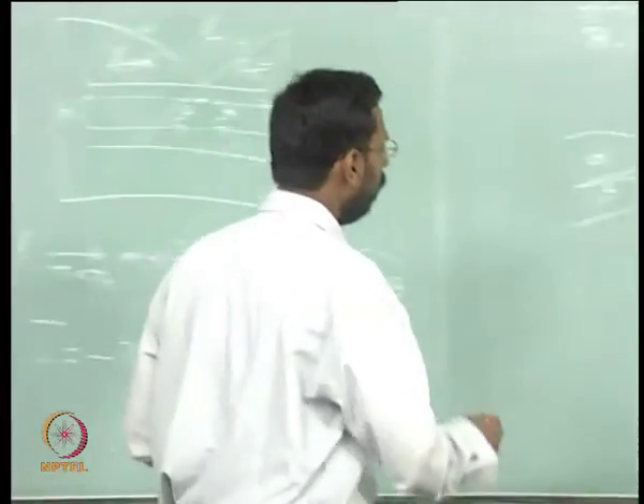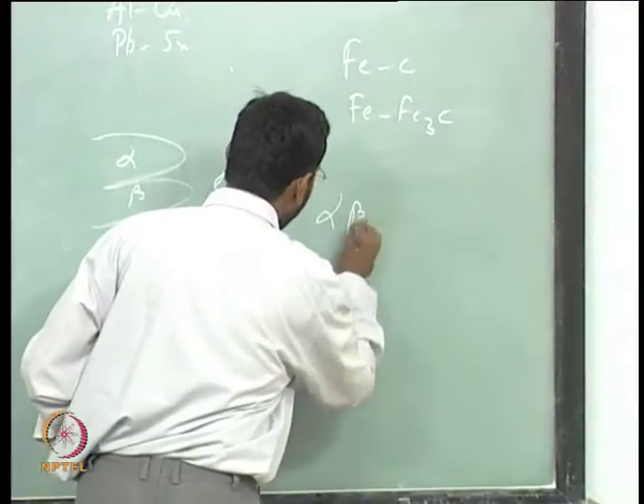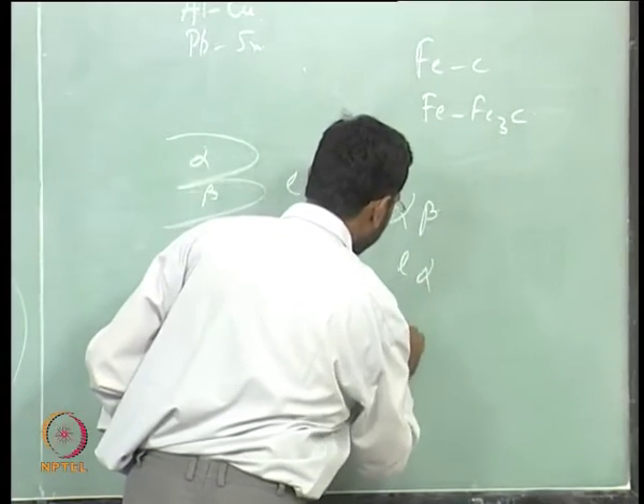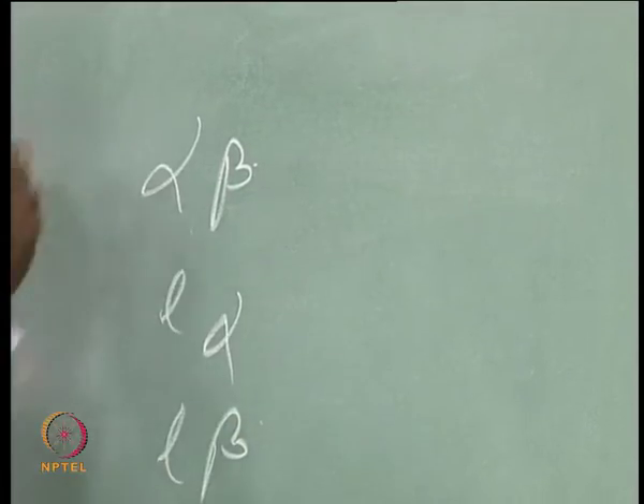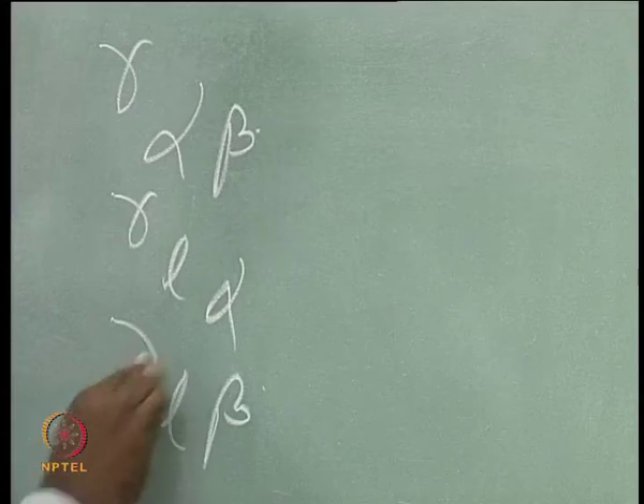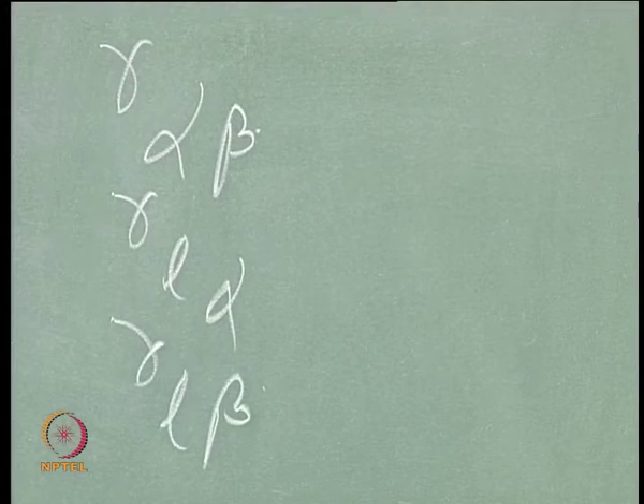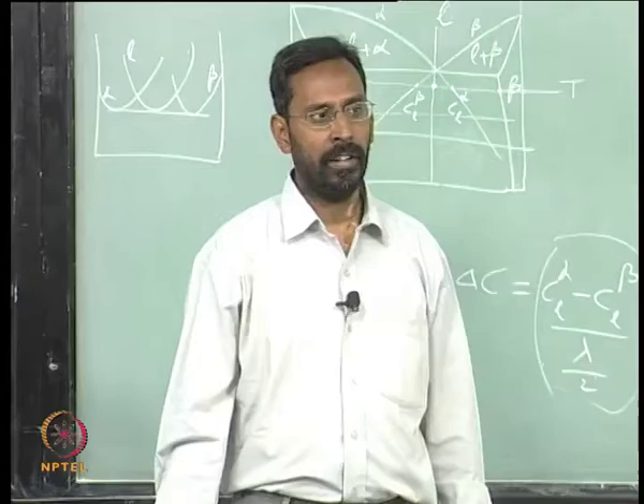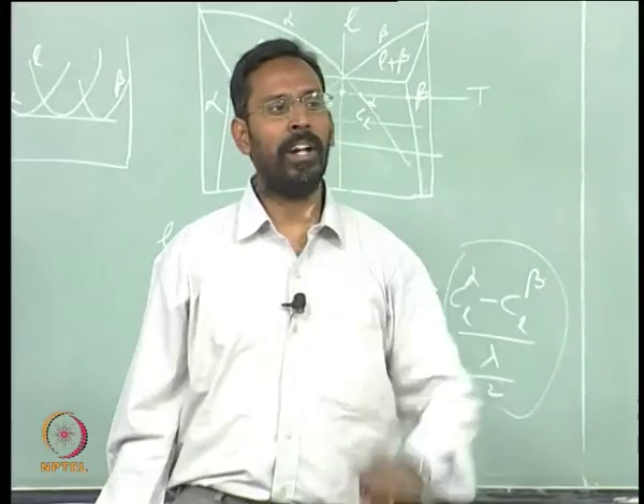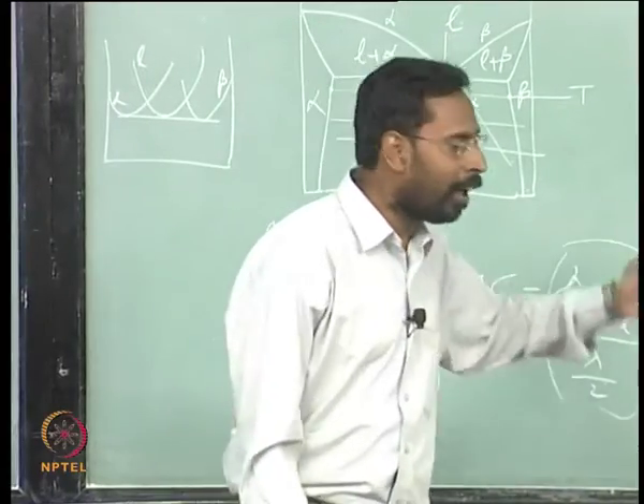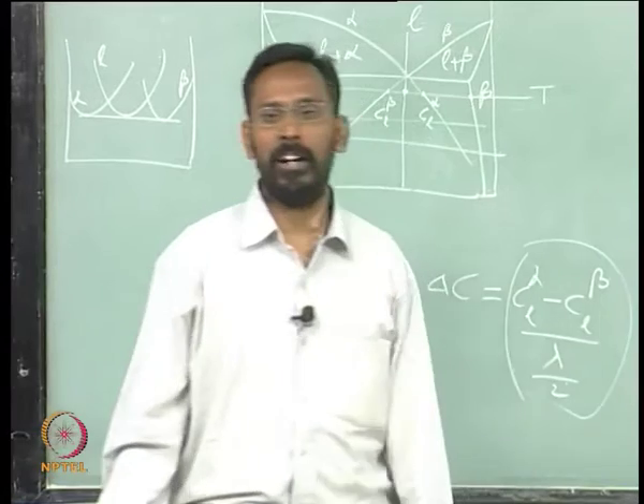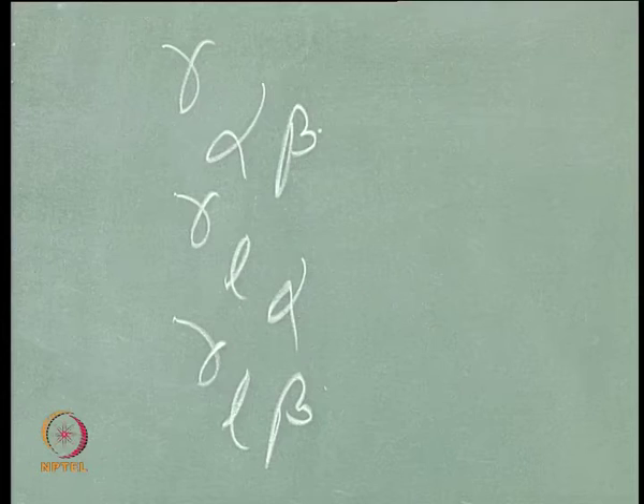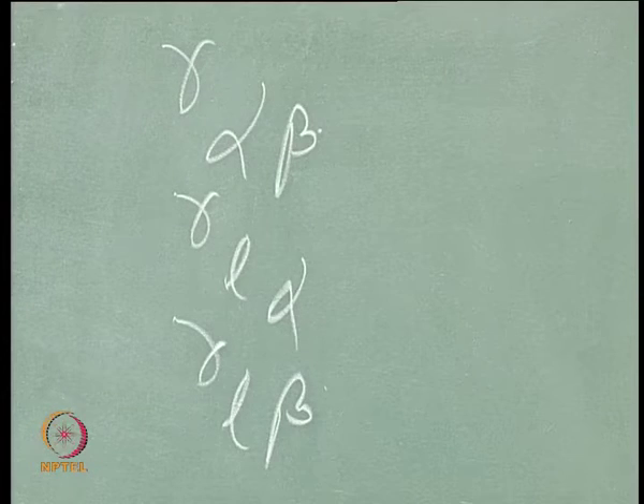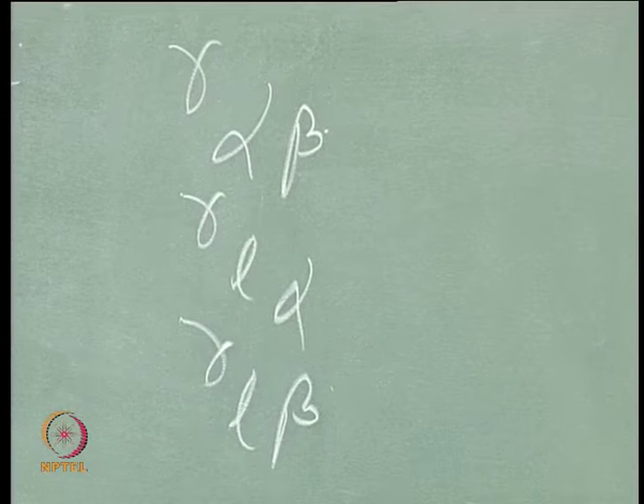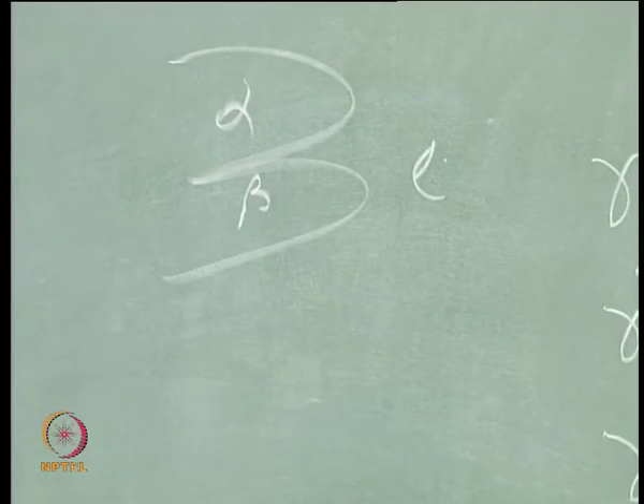So if you look at these 3 interfaces - alpha beta interface, liquid alpha interface, liquid beta interface - all of them are associated with certain interfacial energies, is not it? There is an alpha beta interfacial energy, a liquid alpha interfacial energy, and a liquid beta interfacial energy. We have already seen that whenever you talk about a liquid to solid transformation, the barrier for the transformation is always the interfacial energy.